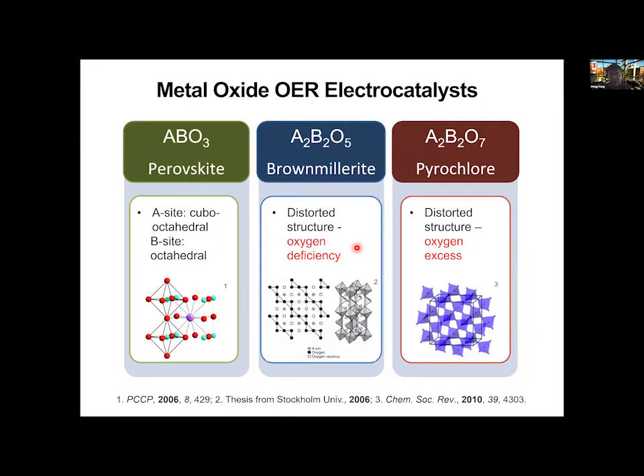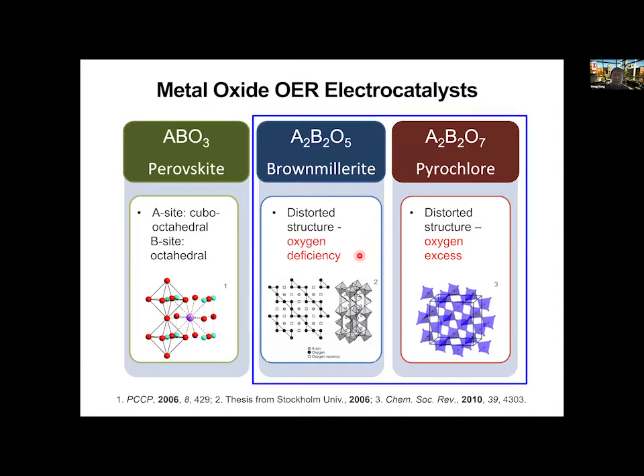As I promised, I'm going to give a quick few-minute introduction to oxygen evolution catalyst development. We primarily focus on oxide-based systems, and two in particular caught our eyes. One relates to perovskite-based OER catalysts, where we try to see what happens if you have mobile oxygen introduced, involving an oxygen-deficient system. The other type is a relatively stable system in acid, the so-called pyrochlore-based system, especially ruthenium-based. That's another one we have worked on recently in the laboratory.